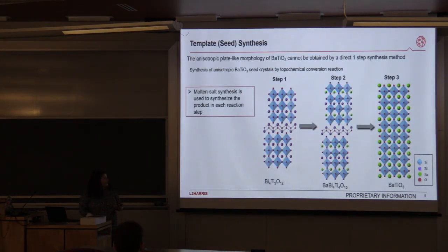Another important step, an extra step, is that we have to grow these template particles. We may only use less than 5%, but they do need to be in a special, highly anisotropic kind of morphology. The way we do that is we take an aurivillius phase and do a molten salt process, where this aurivillius phase typically always grows as a plate-like structure. Barium titanate itself usually wants to grow in a one-step, solid state reaction as a cube. So we use this topotactic reaction series to get our barium titanate, but to keep the plate-like morphology that we have in the first structure type.